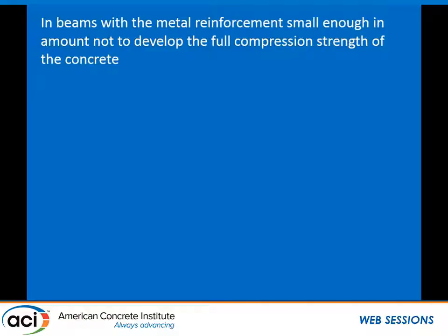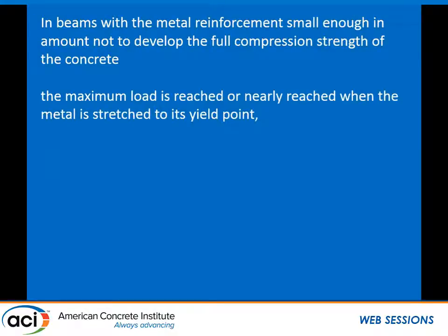In beams with the metal reinforcement small enough in amount not to develop the full compression strength of the concrete, he's talking about under-reinforced beams. And you know, he defined under-reinforced, balanced, and over-reinforced. And then the maximum load is reached or nearly reached when the metal is stretched to its yield point, in other words.